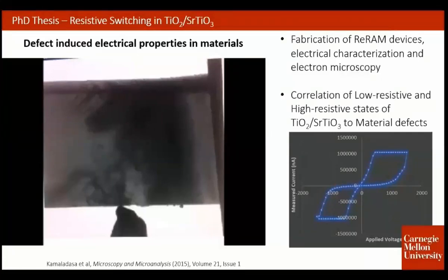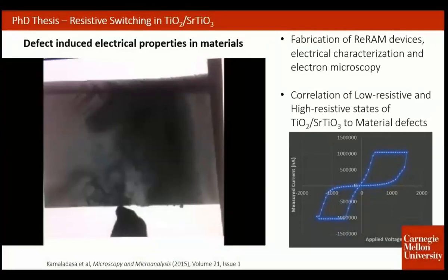So my PhD was on the electrical switching of titanium oxide and strontium titanate. These materials have what's called a resistive switching property, whereby if you apply a voltage, it will change its resistivity from a low resistive state to a high resistive state and vice versa. And so people didn't know what was the cause of this. What's the material property that causes this electrical switch? So I went on and did a few experiments to find this out. And of course, this is the experiment that succeeded. I'm not going to tell you about the thousands of experiments that failed.